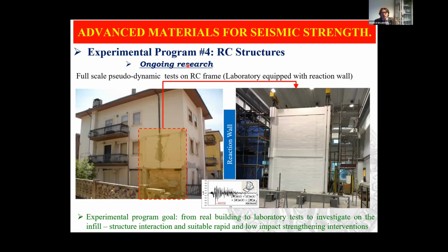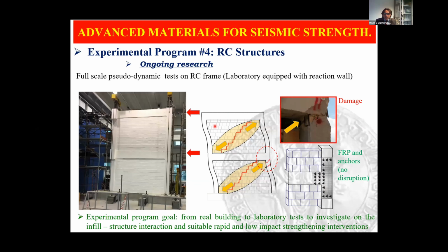Now, an ongoing research that we are performing in a new lab with a reaction wall is a pseudodynamic test on a 2D RC frame, which reproduces a real building frame that was damaged by the L'Aquila earthquake. So we realized exactly the same frame, and we are performing pseudodynamic tests. The idea is to also evaluate the interaction effects within the infills and then to investigate a possible solution based again on FRP plus anchors, wholly applied from the exterior side, again to have a very limited impact and disruption for occupants.